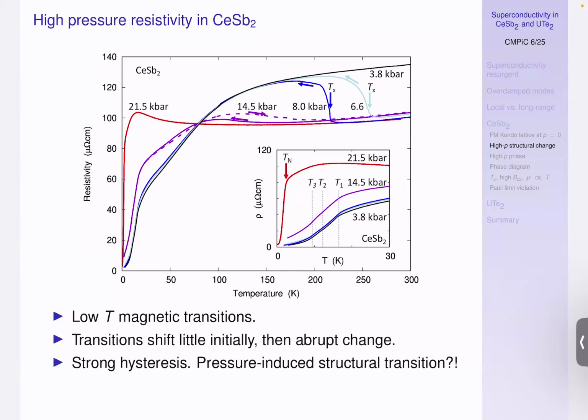So when you fill in the gap, what you find is that this is the low pressure curve, and that's the high pressure curve. And in between, there's a range where the resistivity jumps from effectively the higher pressure to the lower pressure curve, like here. And these are hysteretic. So a bit more thought reveals that this material is actually changing its structure. It's got an ambient pressure structure, and it's got quite a different high pressure structure. And if you're cooling through that transition line as a function of temperature, you see that structural transition as you're cooling.